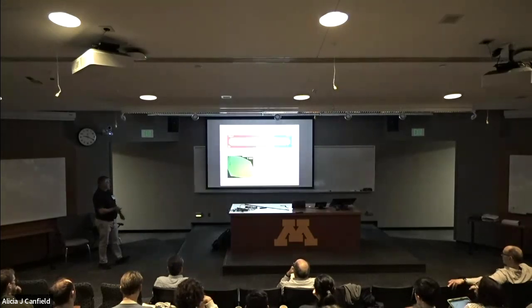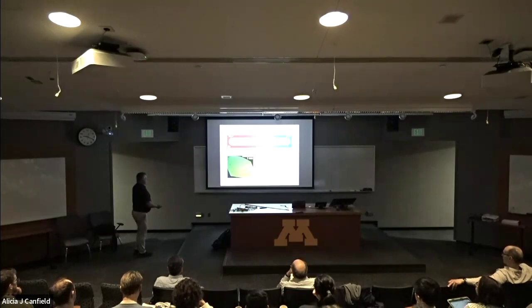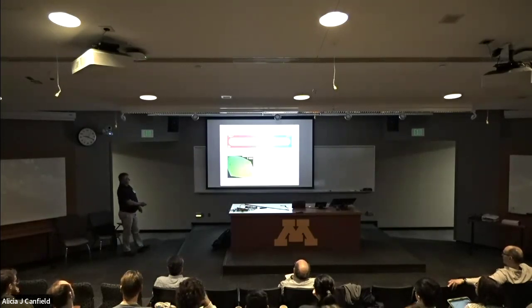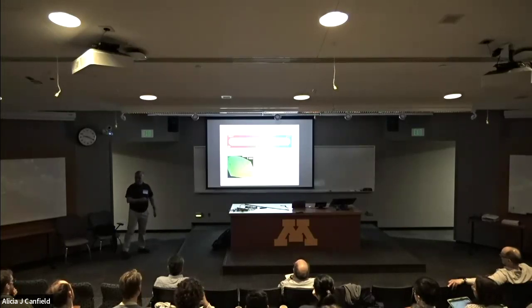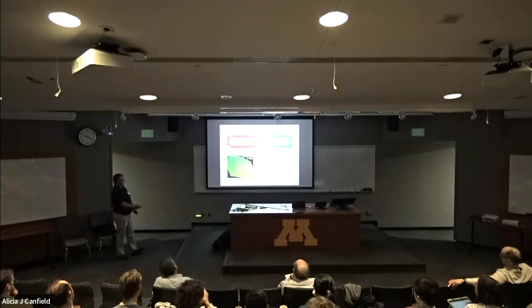So these are, if you like, just materials whose conducting planes are incredibly pure as grown. And that actually makes them far rarer than things nowadays with backscattering protection. So Chris's group then got interested, and this was wonderful. And they did a number of things, which will be on a poster outside. They grew palladium cobaltate by chemical vapor transport technique and managed to make the crystals bigger and even more pure than the ones that we were growing with the metathetic reactions that we were using.